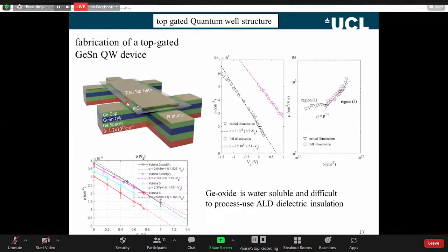What's different here is we've put down an insulator, aluminium oxide, by ALD, atomic layer deposition, and put down the top gate on. And if we repeat those Hall measurements, you can see here this is carrier density p. Traditionally we call holes p-type. Hall density p as a function of top gate voltage. Now it's a hole gas, so it responds by depleting, or reducing the carrier density, from positive gate voltages. These are 1, 2, 3, 4 devices. They all show roughly the same slope here, changing carrier density with gate voltage. This actually might be useful for a CMOS type device because we're only applying about 1 volt, so the device is depleting by about 1 volt.